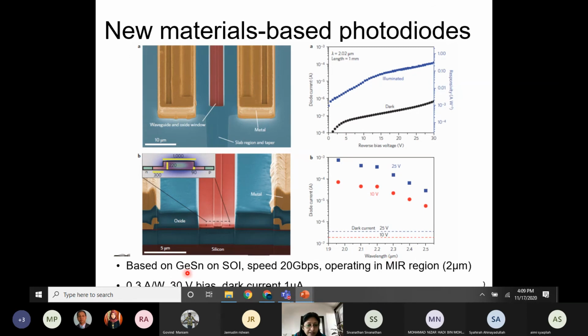New materials. This is germanium stannum on SOI. The speed is 20 gigabit per second. It's operating in the mid-infrared region, which is at 2 micrometer. So the dark current, all right, this is current versus the voltage. Dark current is in reverse bias, and upon illumination, you can see that there's an increase in the photocurrent. So it is using a waveguide and oxide window over here, all right. And this shows the wavelength variation from 1.9 micron up to 2.5 micron for two different voltages. Okay, so higher voltage, of course, it gives higher current.